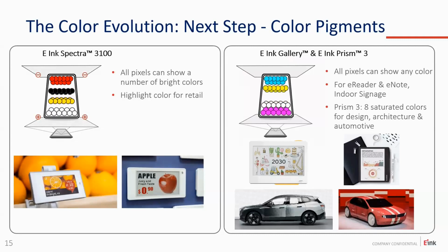The way we do it is you can charge particles with different zeta potentials. You can have very negative, a little bit negative, very positive, etc. Particles can have different sizes, and there can be all kinds of specific interactions between particles. And by engineering this well, you can find ways to always sort them out and create the right colors. Doing this either in a way that creates very bright colors or in a way that is very fast is kind of what we are playing with for different markets.